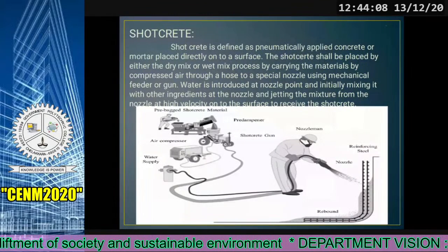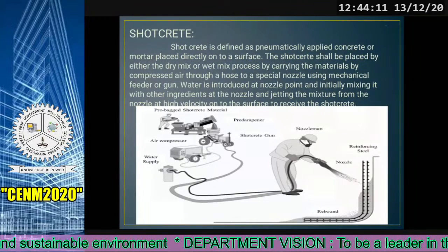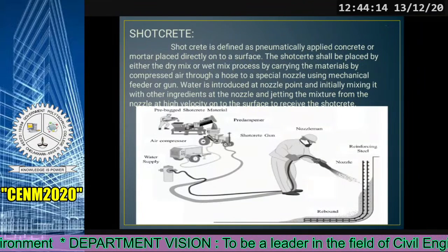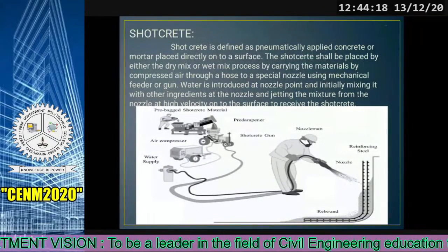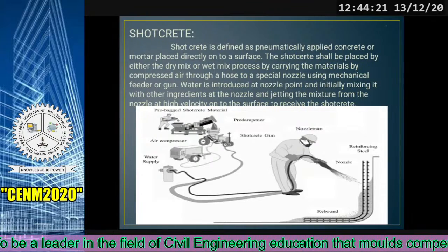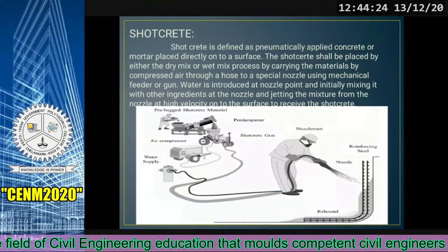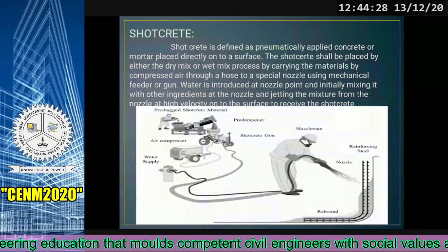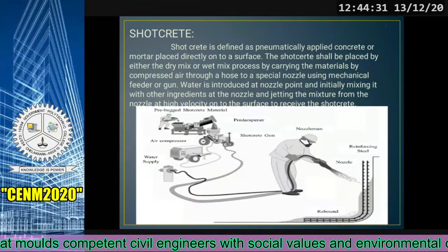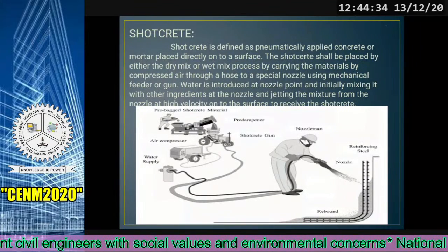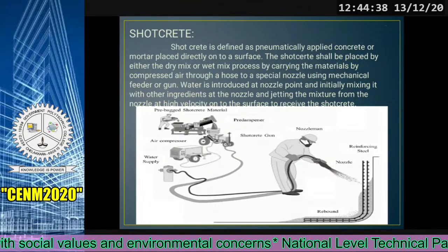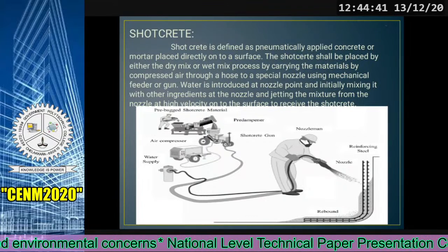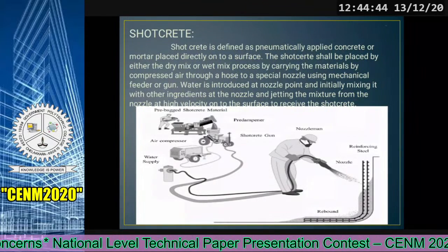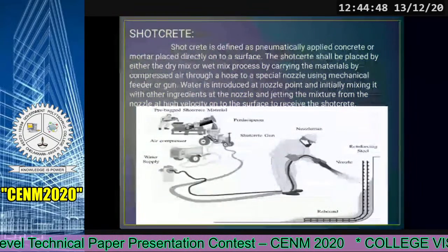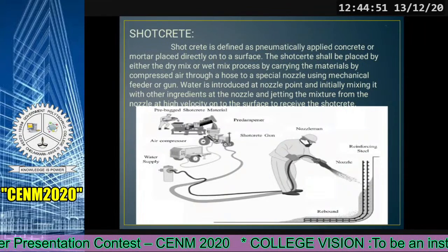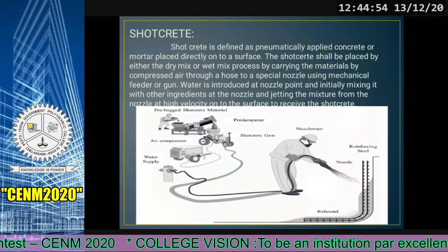Shotcrete is defined as pneumatically applied concrete or mortar placed directly onto a surface. The shotcrete shall be placed by either dry mix or wet mix process by carrying the materials by compressed air through a hose to a special nozzle using mechanical feeder or gun. Water is introduced at nozzle point, mixing with other ingredients at the nozzle and jetting the mixture from the nozzle at high velocity onto the surface to receive the shotcrete. The above diagram shows how the shotcrete process is done in the field. So in our locality, there is a dam at Pollachi, Aliyar Dam. Two years ago, there was one problem at the dam, and it was rectified by using this type of process only.